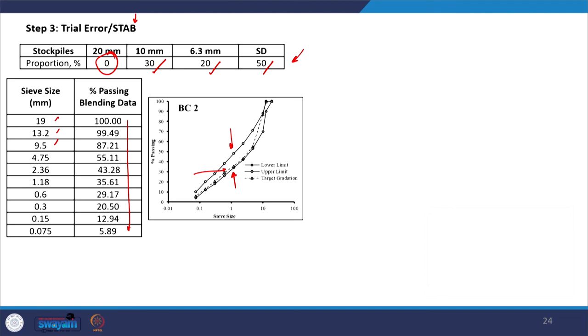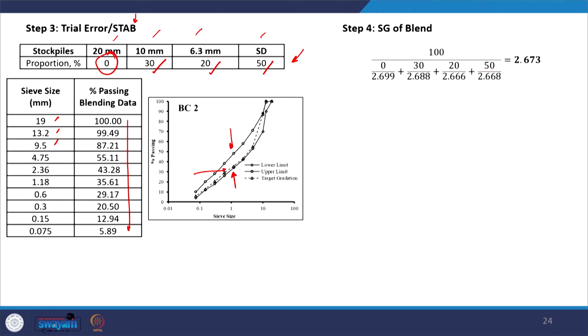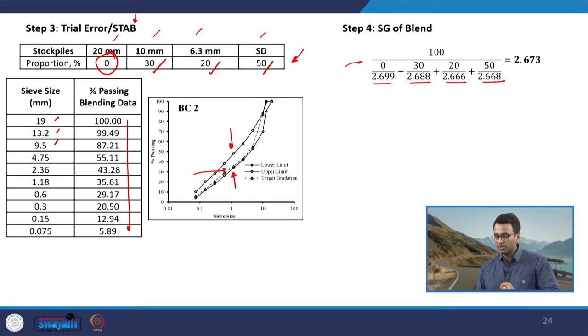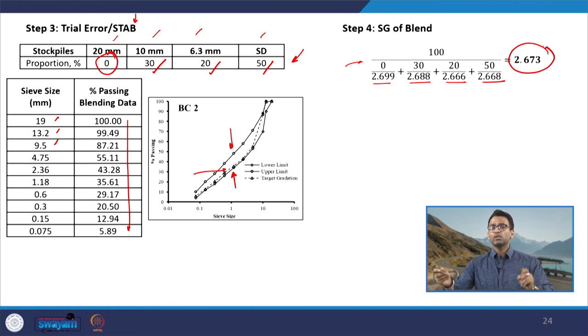With the chosen proportions — 0% of 20 mm, 30% of 10 mm, 20% of 6.3 mm, and 50% of stone dust — the calculated percentage passing for the blended stockpiles falls within the upper and lower bound specification limits, as confirmed by the gradation graph. Now, knowing the blending proportions and the average specific gravity for each individual stockpile, we take another harmonic mean and calculate the specific gravity of the blend, which comes out to 2.673.